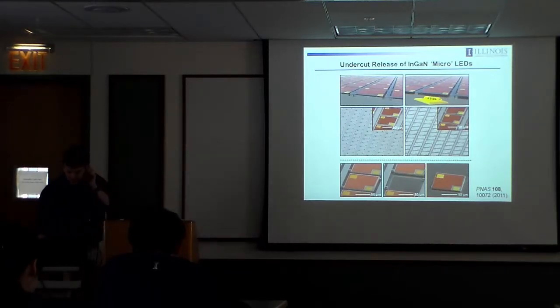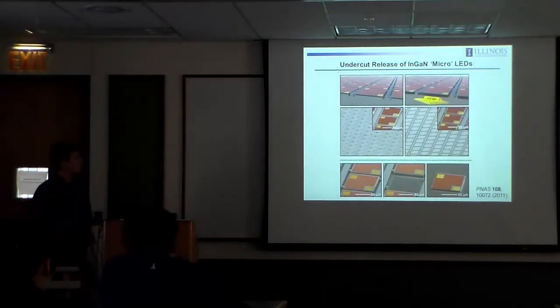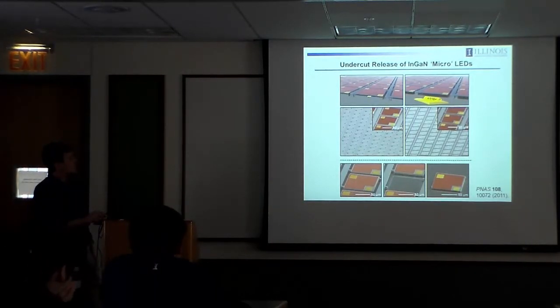So this allows you to make devices that are exceptionally small or big, whatever you want. It's lithographically defined dimensions, so you can go from sort of a conventional LED size in terms of lateral dimensions, 1 by 1 millimeters. The thickness is only about 5 microns, and that's about a factor of 20 to 50 times thinner than a conventional device, because the way conventional devices are built is to use a wafer saw. So you slice up the wafer, so you carry the active material, but you retain that silicon wafer substrate, so much, much thicker. But you can do large or all the way down to small. So this is about as small as we can do with the academic facility, but in principle you can go much, much smaller than this if you want. It's about 25 microns on a side. If you have better lithography capabilities, you can go smaller.